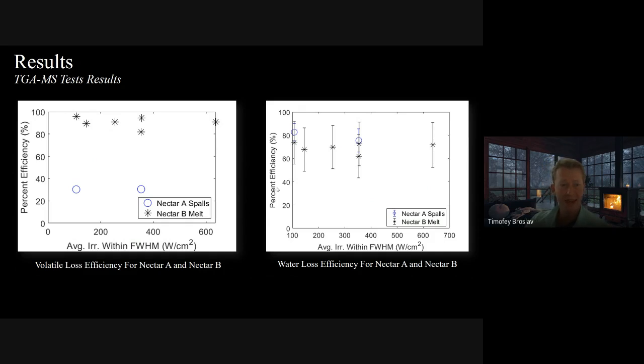I would say Nectar A. This also contains water loss efficiency on the right, and volatile loss efficiency on the left. Nectar A has low volatile efficiency compared to Nectar B, obviously because it did not get as hot before spalling, and also because most of the volatile mass loss wasn't just water, it was also carbon dioxide and some sulfur compounds.